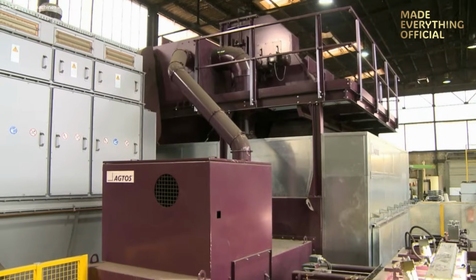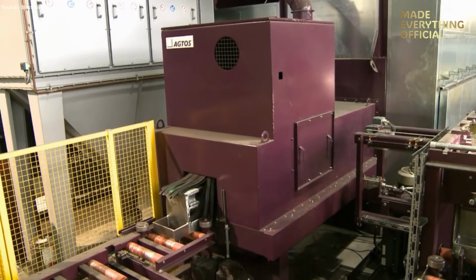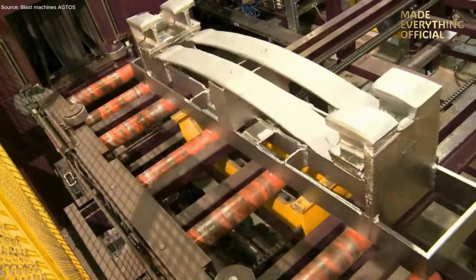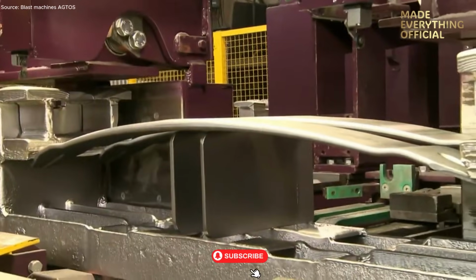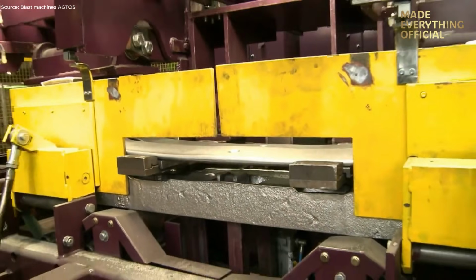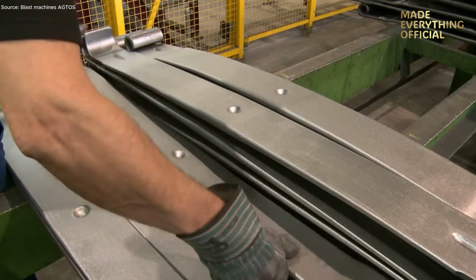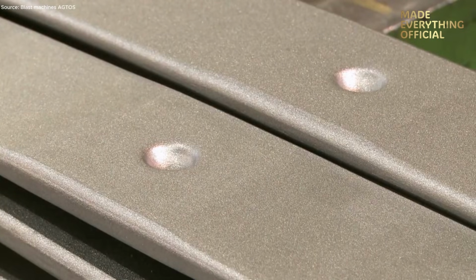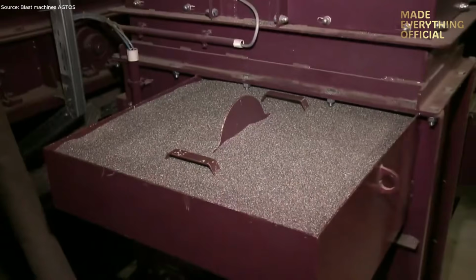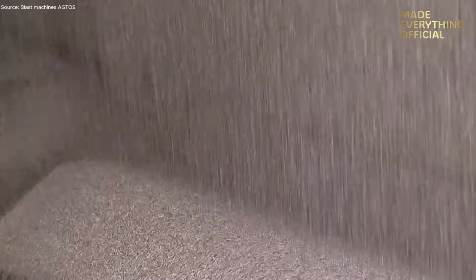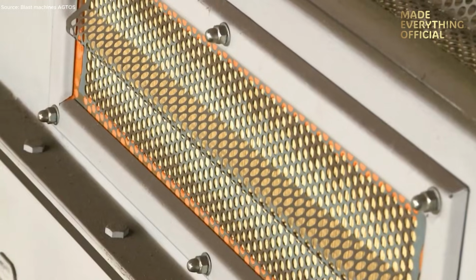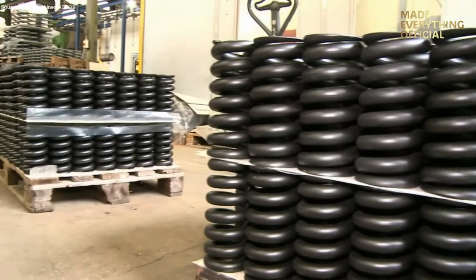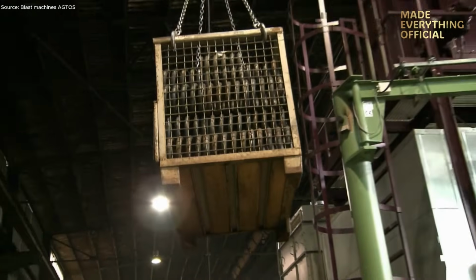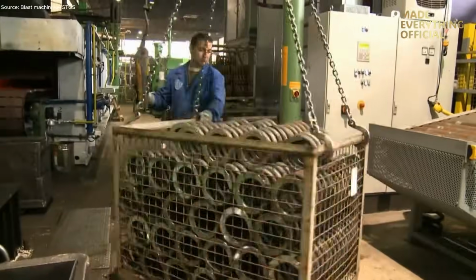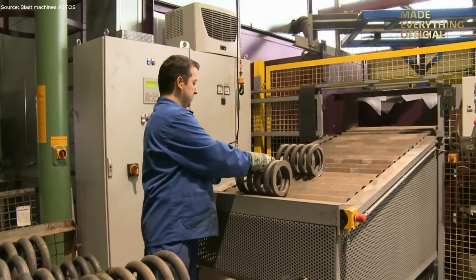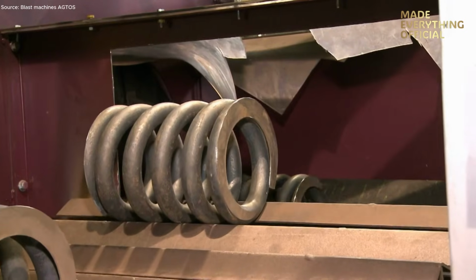As they enter the blast zone, the tension surfaces and edges are hardened at feed speeds between 3 and 10 meters per minute. The vestibules are lined with heavy, wear-resistant rubber curtains to prevent blast media from escaping. A noise protection booth nearby reduces sound from 90 decibels to 80 decibels, creating a safer workspace. Inside the chamber, the AGTOS high-performance turbines deliver intense, controlled, shot-peening energy. The turbines begin in idle mode, ramping up only after the workpieces enter, saving energy and avoiding unnecessary media wear.